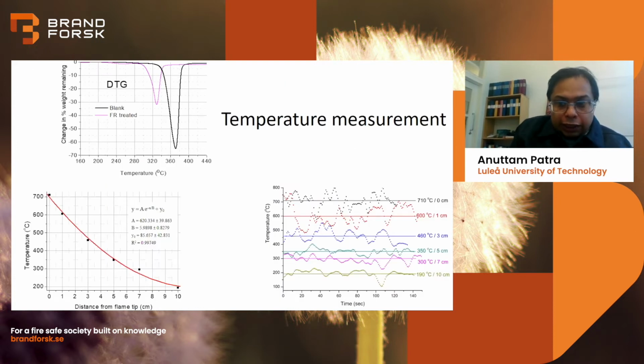We checked the temperature variation over distances, from the flame tip to 10 centimeters. The temperature was measured with a thermocouple 0.25 millimeter thick. When the distance between the flame tip and the measurement was 10 centimeters, the temperature was 200 degrees.